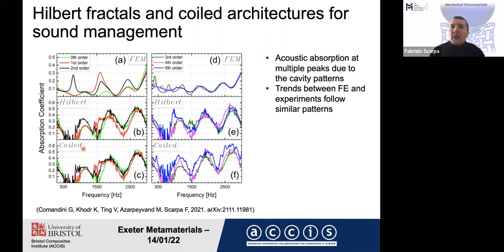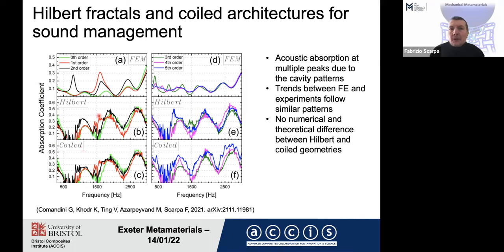And in general, we can also see that the trends between finite elements and experiments follow pretty much the same pattern. But what is important to keep in mind is that the behavior between these Hilbert fractal and the coiled architecture are the same, at least theoretically. And also you can create, by tuning the patterns, these peaks in terms of acoustic absorption. And those peaks correspond to the resonance of the air cavities inside the fractal.